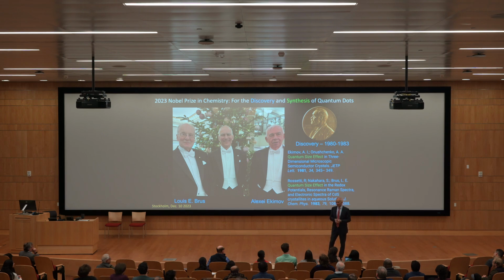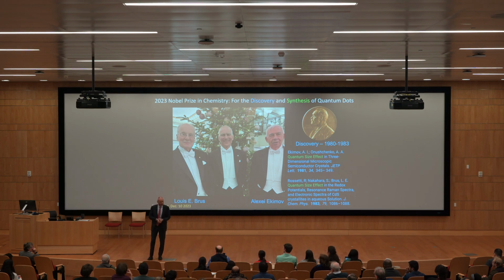And the reason why it was the case is because the initial samples were made under dry ice temperatures to try to prevent the crystals from going too fast, so they would stay as small particles. And it was made in water. And if you know anything about semiconductor synthesis, you really don't want any water around. Because what happens is you make oxide, especially if you have a nanometer-sized particle and you put it in water. Pretty soon you're going to have cadmium oxide. You're not going to have cadmium selenide. And if you want your semiconductor to be crystalline, you probably don't want to grow it at liquid isopropanol, like dry ice temperature. You want to heat it up a little bit.